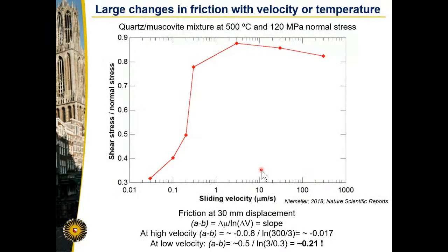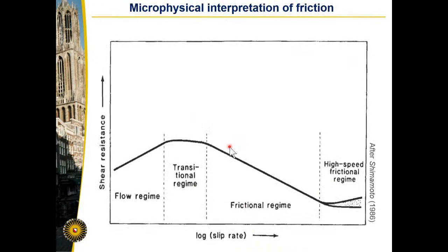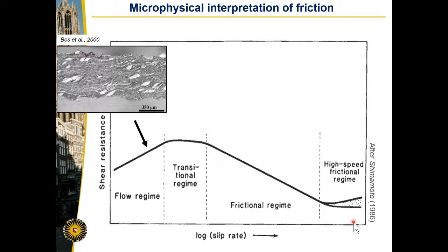So looking at the profile, I have to speed up a little bit, I see. You can see this pronounced velocity strengthening that moves over to a velocity weakening, and I didn't reach this velocity strengthening regime. Now, this was already recognized by Toshi Shimamoto in the 80s, where he suggested that we have a flow regime, a transitional regime, a frictional regime, and then a high-speed regime.